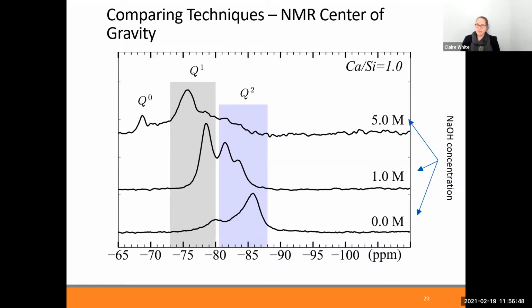there is a lot of interaction with calcium ions around the silicon centers, away from the silicates. And in terms of hydroxyls, there's probably not too much going on in there. People have looked at this quite extensively when it comes to cements and NMR analysis. I fully understand that peak positions can move based on the local environment around the silicon centers. What I will say is that